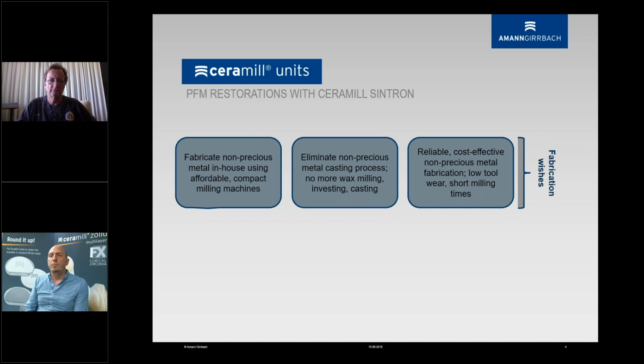So looking at the process, there were fabrication wishes, and one of the wishes was to do that in-house using affordable compact milling machines. The mills have already been in the field, and there's plenty out there. And to eliminate the non-precious metal casting process, basically for those reasons we were talking about: no more wax milling, investing, casting. Of course, it's always an option, but the sintered metal is just on a different quality level. The process was supposed to be reliable, cost-effective for non-precious fabrication, and hopefully have low tool wear with short milling times. That was the challenge with the hard-state metals.